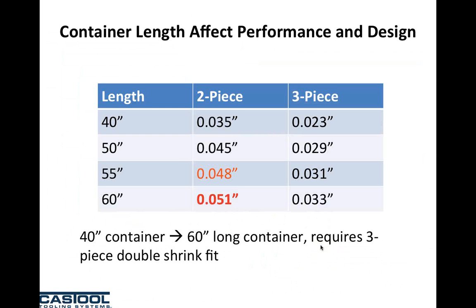As we get into 50 inches, we're probably still okay as long as it's not soft alloy with 45 thou expansion of the bore. As we get into containers that are 55, 60-inch long or longer, there's too much mechanical expansion in the bore to be able to put a dummy block in there and control the aluminum and aluminum flow-by. So in all cases, when we start getting above 50 inches, we recommend going to a three-piece container to be able to control the expansion. And again, if we're doing soft alloy, we would tend to do it sooner with shorter containers.